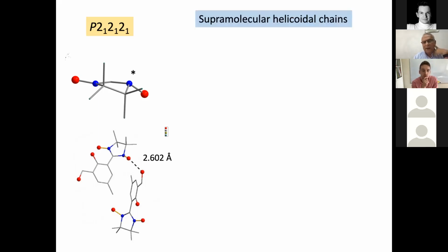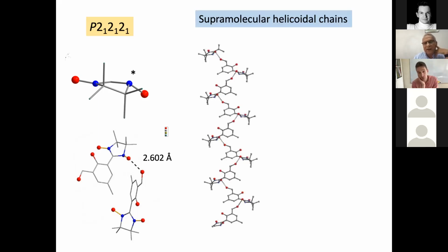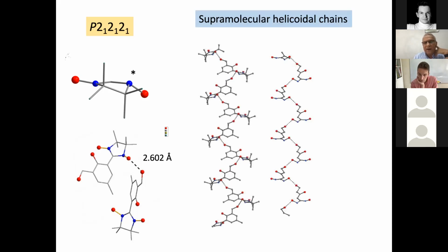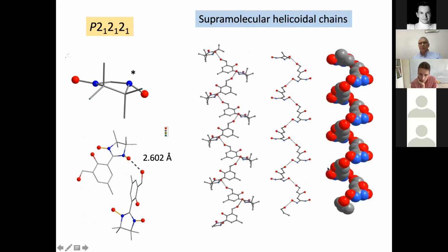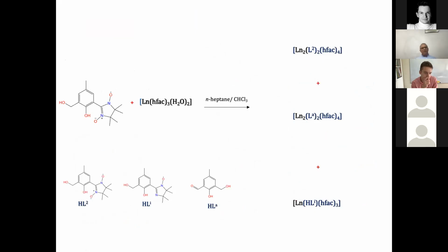And we identified indeed supramolecular helicoidal chains. And to be more visible, we simplified this perspective view with this one by removing carbon atoms. And now the formation of the supramolecular helicoidal chains is clearly shown in this picture. So the origin of this crystal packing is the fact that we have this nitrogen atom frozen in a chiral configuration here. So we have our ligand. Now we can proceed to synthesize the complexes.